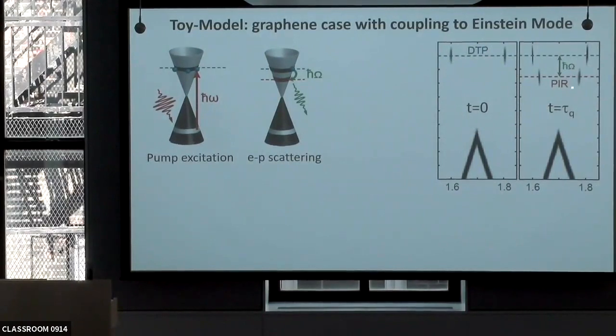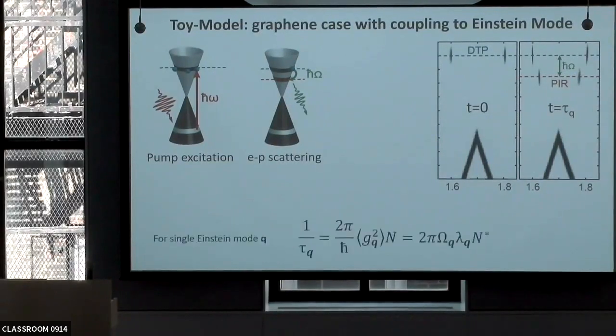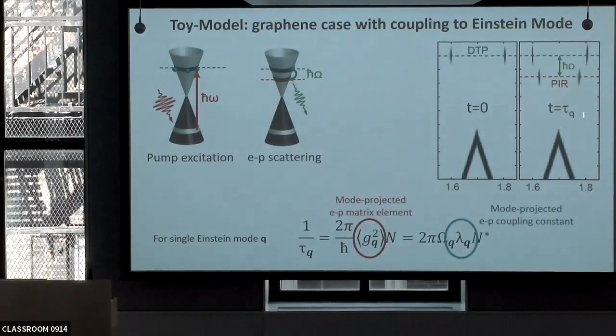And then we wait. After a certain amount of time, related to the electron-phonon scattering time, you would see that the population, the intensity, is transferred down in discrete steps, and this discrete energy difference is the phonon energy, if you have an Einstein phonon in the problem. And then again, what you would like to do is go from this electron-phonon scattering time, if you can measure it, and extract G, and then in principle you can also extract lambda once you introduce your electronic densities.